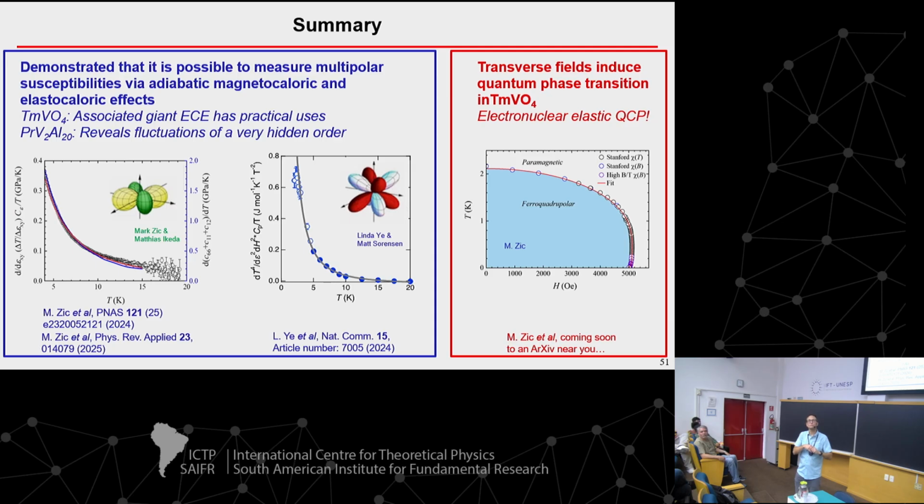But if you think you have some finite polarization of the nuclear ground state at 30 millikelvin. Oh yeah, 100% for sure. All this backbending happens about a factor of 10 larger than that splitting, and it finishes about a factor of 10 less than that. So the splitting, call it 50 millikelvin, and around roughly 500 millikelvin is where you begin seeing effects, and it's all done by 5 millikelvin. Interesting. Yeah. Okay, thanks.